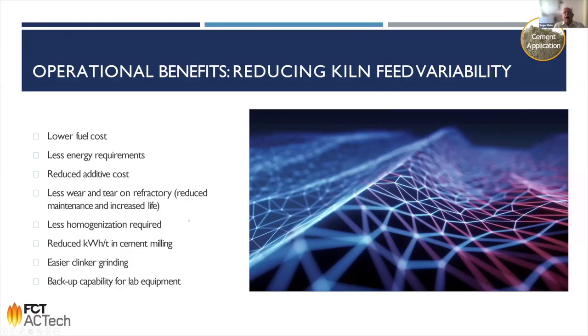And the benefits are for you, I think, very obvious: having a very low standard deviation in the feed of the kiln, you reduce the fuel cost, you need less energy, you avoid a lot of issues. It will have a very positive effect on wear and tear. Maybe, and this depends on the installation and your design of the plant, you need less homogenization. But you have also further down in the process a lot of advantages. For example, this can lead to a reduced energy consumption in the cement milling process by having a more consistent material.